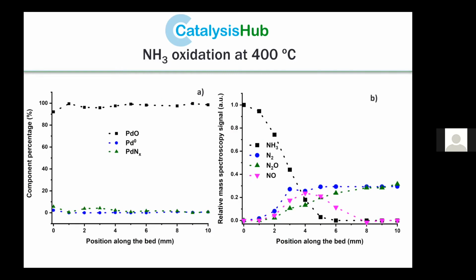Palladium nitride pretty much disappears at this temperature, and it's only palladium oxide as a species, and this species is completely unselective toward nitrogen, and N2O and NO appear as we increase the temperature.